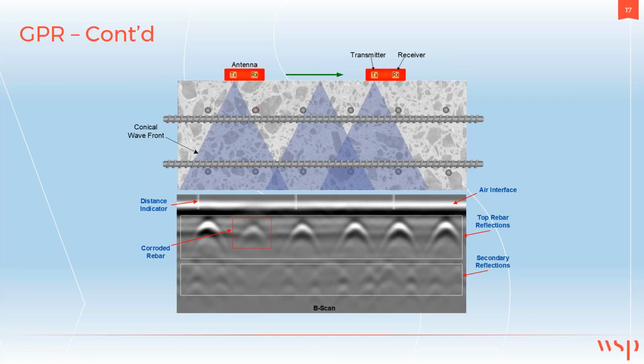Note the second bar from the left has a very light signal. That would be typical of a bar that has perhaps corrosion product or voids around it. What that's indicative of is that corrosion product or voids can tend to dissipate the electromagnetic signal and end up with a lower amplitude reflective response.